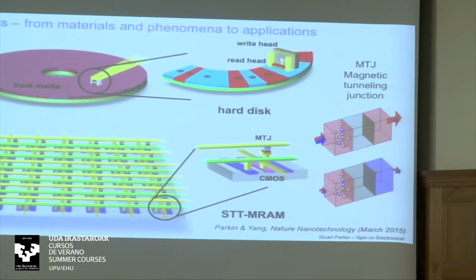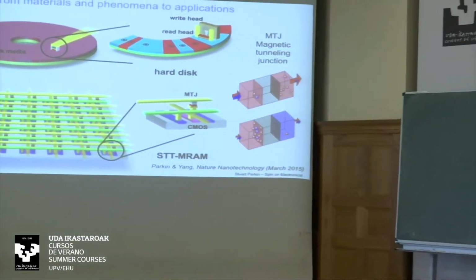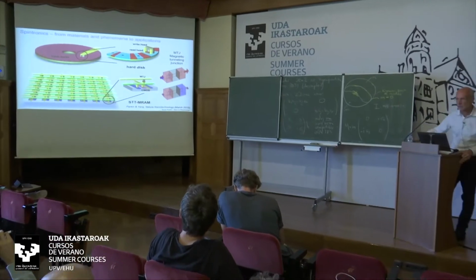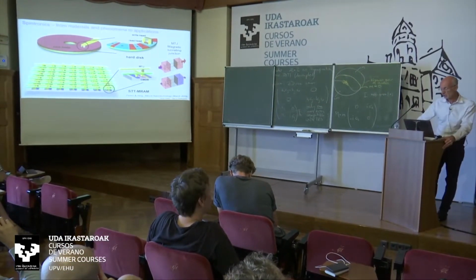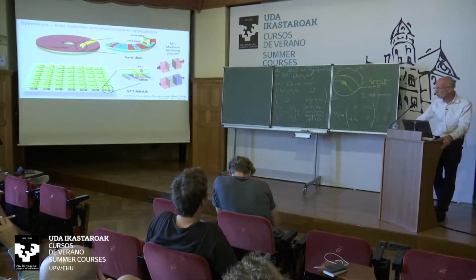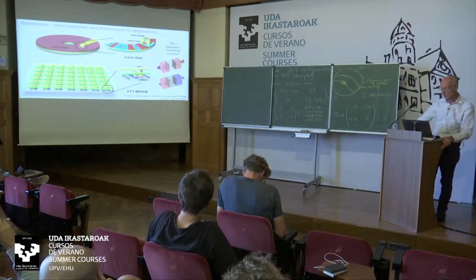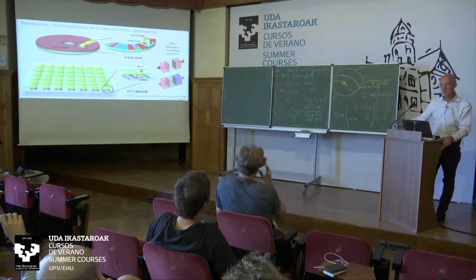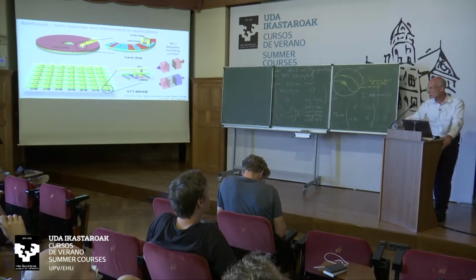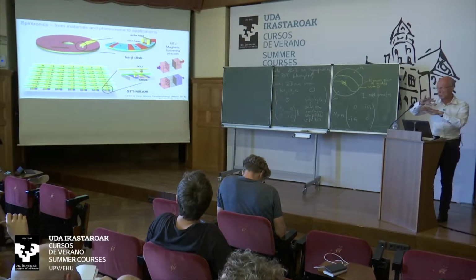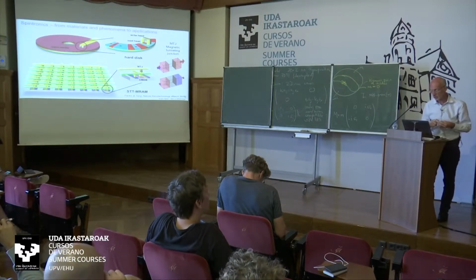This leads to very, very efficient creation of spin polarized currents of up to about 96% spin polarized currents in this very simple device. Using this device, the resistance of the tunneling junction depends on whether the magnetic electrodes are parallel, as shown in the upper cartoon, when the currents can flow more easily, or whether antiparallel, when effectively the current can be nearly suppressed. And this means we have a device that has two states, a 0 and a 1, which we could use as a memory element. And then you can build these magnetic tunneling junctions into a standard so-called cross-point array, as shown here, where you have a series of wires which are crossed with each other, and at the cross point, one can insert this tunneling junction device.